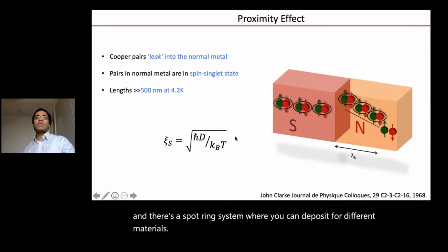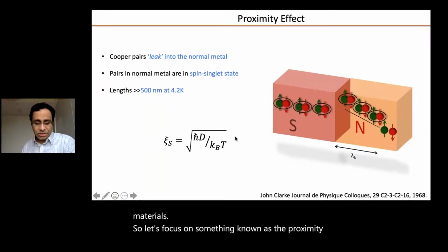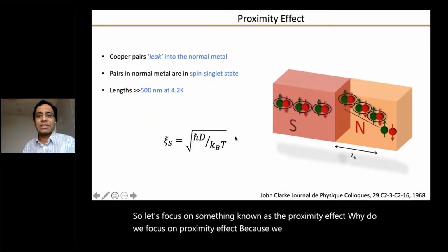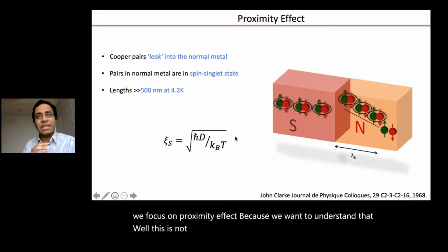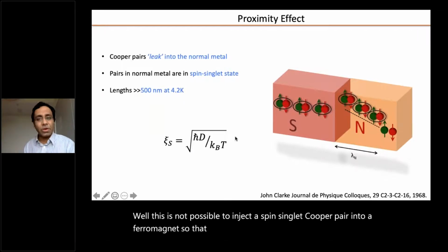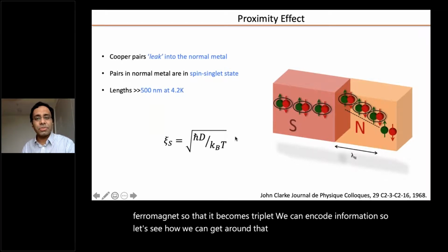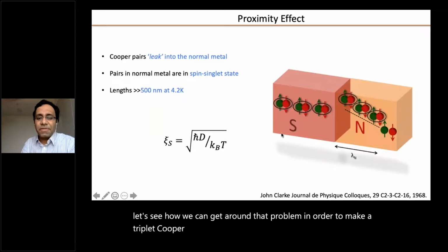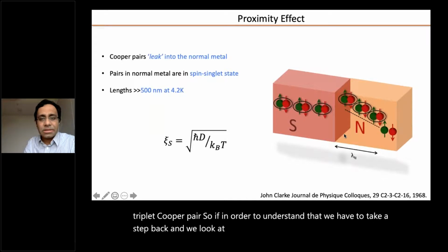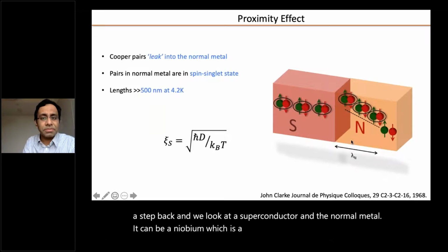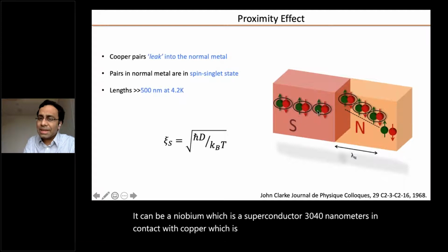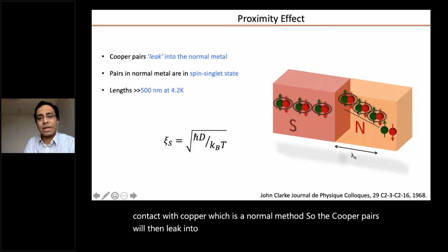So now let's focus on something known as the proximity effect. Why do we focus on the proximity effect? Because we want to understand that, while it is not possible to simply inject a singlet Cooper pair into a ferromagnet so that it becomes triplet, we can then encode information. So let's see how we can get around that problem in order to make a triplet Cooper pair. To understand that, we take a step back and look at a superconductor and a normal metal. It can be niobium, which is a superconductor, 30-40 nanometers in contact with copper, which is a normal metal. The Cooper pairs will then leak into copper and make the copper superconducting.